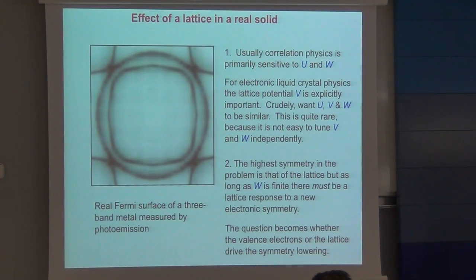So you can't, in the solid, define these liquid crystalline states purely or easily in terms of symmetry, and I think there's a lot of confusion about that. You end up with this kind of chicken and egg problem, where what you're trying to decide is, did this lowering of symmetry have its origin in the electron-electron interactions, or did it have its origin in structural chemistry? Right, but that's a decision you have to take, and there's a lot of completely wrong and very loose language in the literature about this. You always have to be aware there's going to be a back coupling.